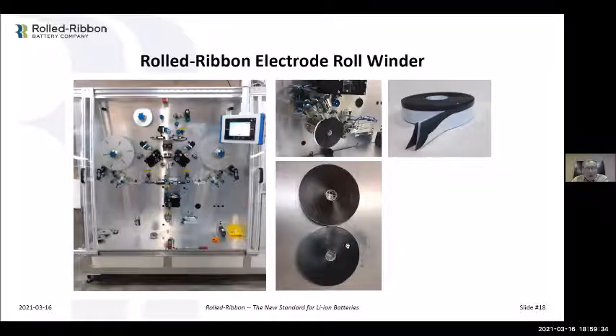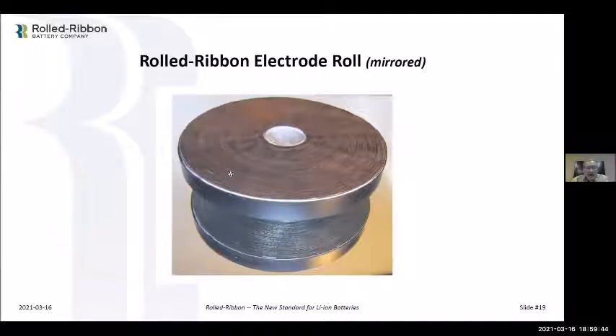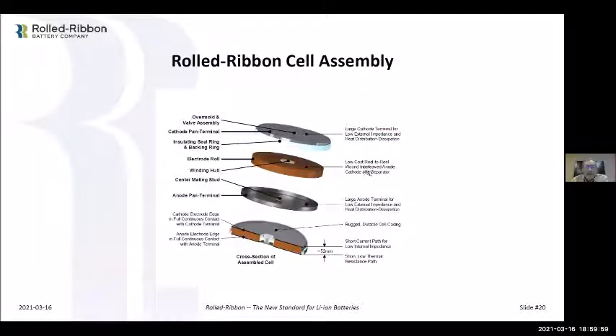And the cathode, in this case an LFP cell, is coated on aluminum. So you can see the edge of the aluminum on the other side. I can see it a little better here, so we have a mirror down below. Here's an electrode roll that was wound on the winder, and you can see the copper side and the aluminum side, anode and cathode. We take that electrode roll and drop it in between the two pans with a seal in between. We put that under pressure, and then we crimp seal it. As you can see here on the edge, there's the crimp seal along the edge.